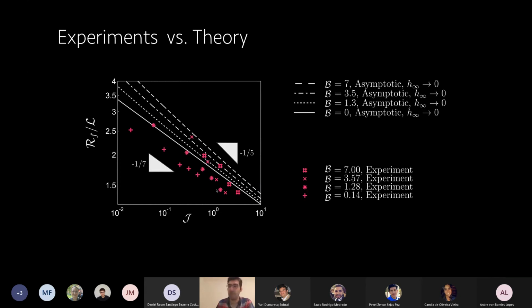There are a lot of difficulties in doing these experiments, in particular with the small Bond number experiments, because the droplets are very small. So doing proper experiments is hard. Another difficulty in such experiments is that finding material properties, in particular surface tension of these materials, is not very easy. It's not actually trivial at all. Hence, some experimental discrepancy. But the last theoretical point I want to go on is that all the viscoplastic lubrication theory that I talked about is pretty shallow, right? So it's literally the shallow limit.